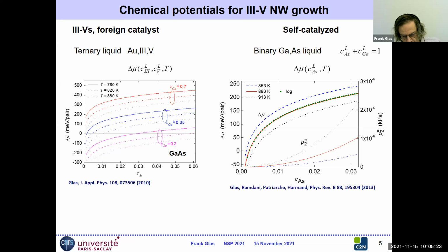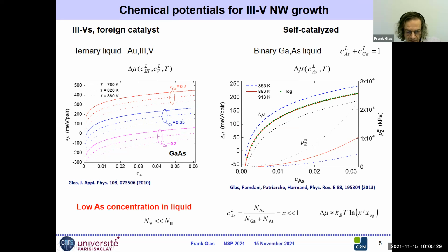And anyway, arsenic and group 5 in general are very volatile species, so you cannot accumulate a lot in the liquid. Because the number of group 5 is very small with respect to the number of group 3, the concentration is more or less proportional to the number of group 5 atoms, the number of arsenic atoms. So in the following, I will speak indifferently of the number of arsenic atoms in the liquid or the atomic concentration of arsenic in the liquid, which is very small with respect to 1, because the two are more or less proportional. And one thing which is useful to remember is that this difference of chemical potential, in very good approximation, scales as the logarithm of the group 5 concentration.